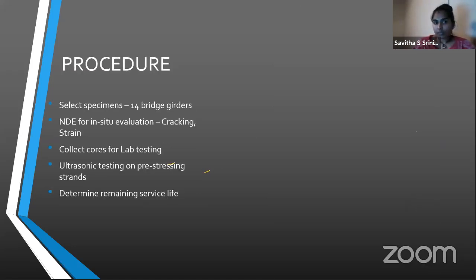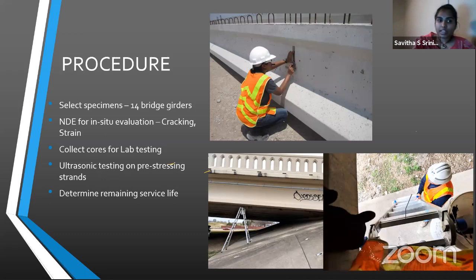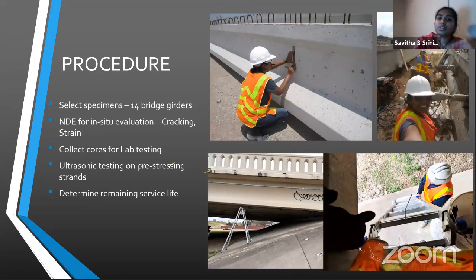So the procedure that we followed was selecting specimens. So we had around 14 girders, which we went and examined. So we did NDT on these girders. We took cracking measurements, strain measurements. We did ultrasonic pulse velocity, resistivity, and things like that. And then the next one was we also collected cores. So the picture that you see here is me and my undergraduate research assistant collecting cores.